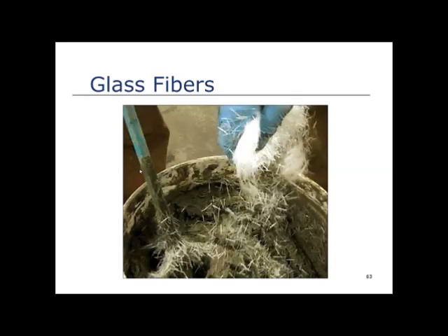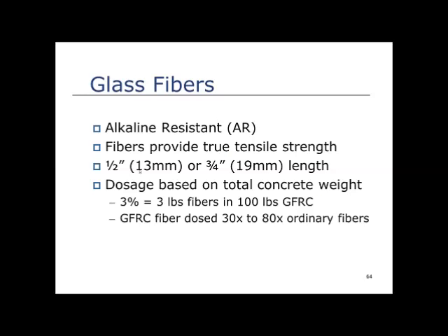And of course the fibers are essential. You have to have those. The glass fibers are alkaline resistant, developed for GFRC. If any of you are familiar with regular fiberglassing, how they make tubs and boats and spas, or sink molds for the concrete countertop industry, those use ordinary glass, sometimes called E-glass or S-glass, and that kind of glass cannot be used in concrete. The alkalinity of the cement embrittles and actually starts dissolving the fibers. So it was in the early 60s, I believe, that alkaline-resistant glass fibers were developed that would prevent that from happening. They have to alloy the glass with zircon, and the zirconia content makes it expensive.